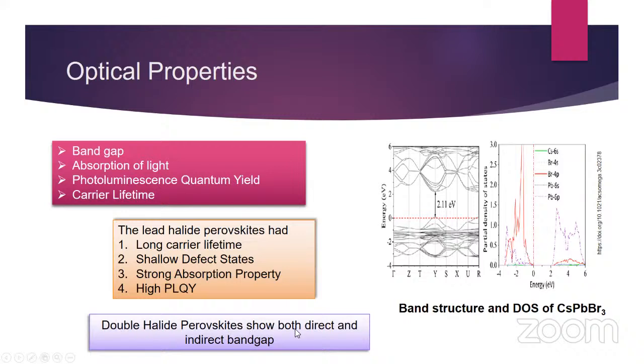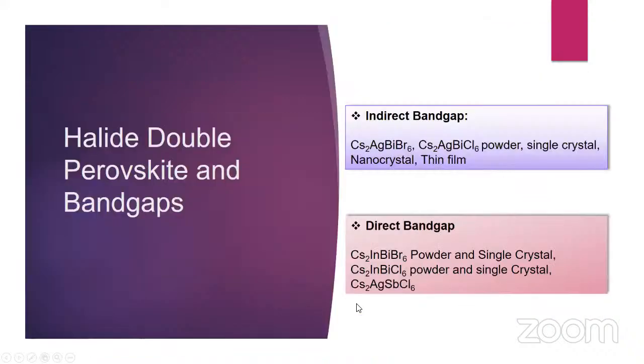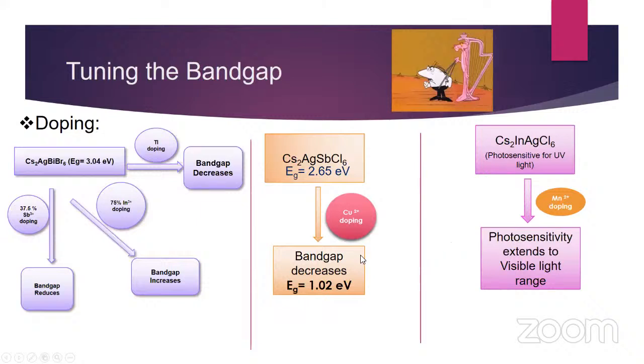Our double halide perovskites show both direct and indirect band gaps. Here I have mentioned the indirect band gaps shown by these double halide perovskites, and these materials show direct band gap. According to our need, or more properly, to make devices, we often have to tune the band gap. Tuning of the band gap implies controlling the band gap according to our need. Here are some methods to tune the band gap of double halide perovskites.